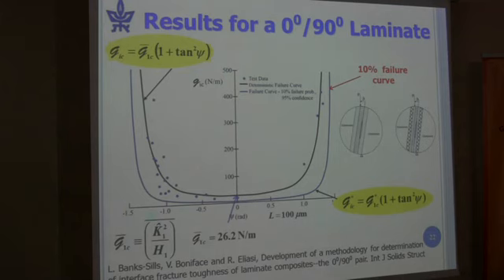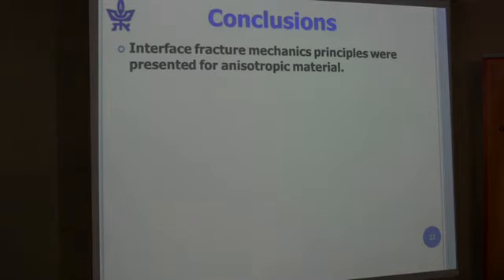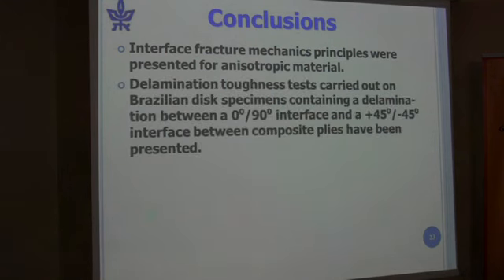And then for our new failure curve, which we have a 10% probability of failure below it, this is this curve, in which G1C star is 5.1 newtons per meter. And so we will conclude that we have looked at the interface fracture mechanics principles for anisotropic material. We carried out tests on Brazilian disk specimens. We did it for the 0-90 interface, and that's what I presented to you.